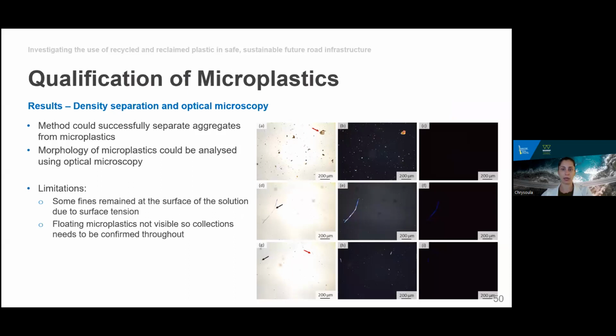We could also successfully collect microplastics from the solution following the density separation, which then could be analyzed under an optical microscope, for example. Using this method, however, we were also collecting fines that remain floating on the surface, possibly due to surface tension. So when looking under the microscope, we need to be careful that what is analyzed is indeed microplastics. Using methods such as polarized lenses or UV light, among others, could help with this. In addition, we need to note that the floating microplastics were invisible to the naked eye, so collection needed to be confirmed throughout.